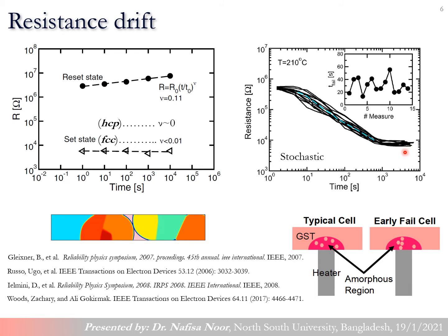So the reason behind that is when we have these crystallizations in the amorphous region, there are some crystalline islands that nucleate, and after these nucleations, these nucleated crystalline islands grow in size. For example, here you see that one island is growing, and as other islands are popping up, they are all growing together and merging together.